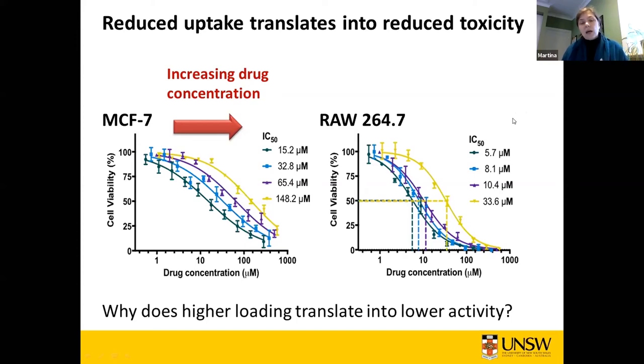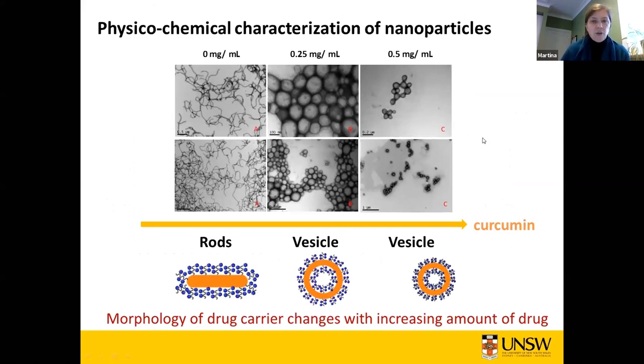So why does higher drug loading translate into lower activity? And so we really need to look a little bit more careful. And this is now a very extreme example because we saw immediately what's happening. So what we actually started off with, we wanted to load drugs into these rod-like micelles here. And now when we put in drugs, it actually changed shapes. But the more drugs we had, the smaller your nanoparticles became. So we could sort of understand that when you go from one shape to another one, that it changes the cellular uptake. What we couldn't understand is when we go smaller in size, why the uptake gets lower, although it should actually have gotten better.